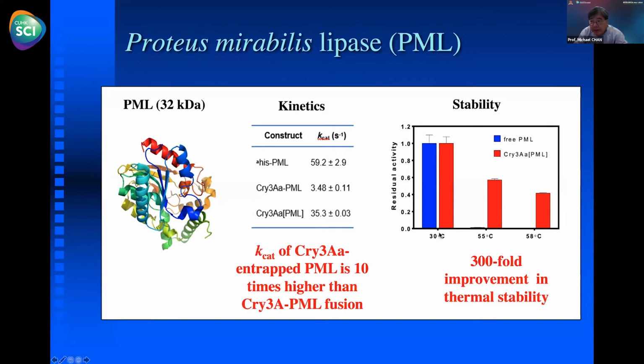But the key advantage, at least for this system, is its ability to enhance the stability of the enzyme. So here's the free PML protein in blue, and in red is the PML entrapped in Cry3A. And you can see at 55 degrees, the free PML protein is dead. But for our PML trapped in Cry3A, you still have about 60% activity. And so we think this is because when you entrap the protein within the crystal, you prevent the protein from unfolding, and thus you're able to enhance its stability. And that's important for industrial catalysis because you can raise the temperature.